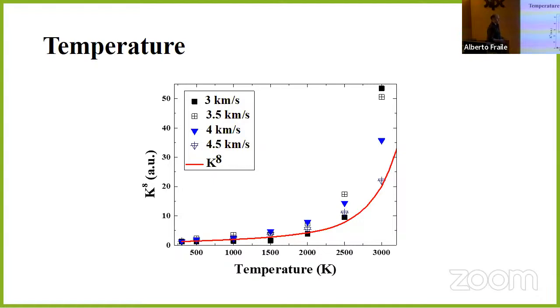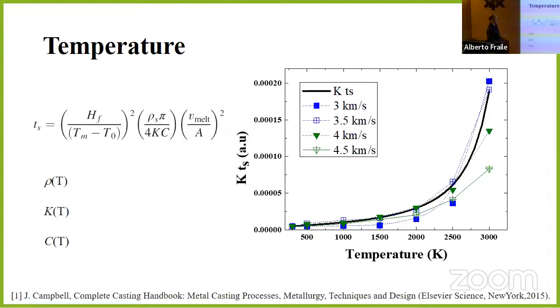It can be fitted to the compressibility to the power of 8, but I don't have a reason for that. So this is something that I'm doing, some numerology. This is just to show that it goes up, and we don't know yet how to fit or how to explain this properly. Of course, one can invent a more complicated model, like, for example, compressibility times the solidification time. And then we don't need an 8 in the compressibility. Just compressibility times the solidification time fits quite well the results.